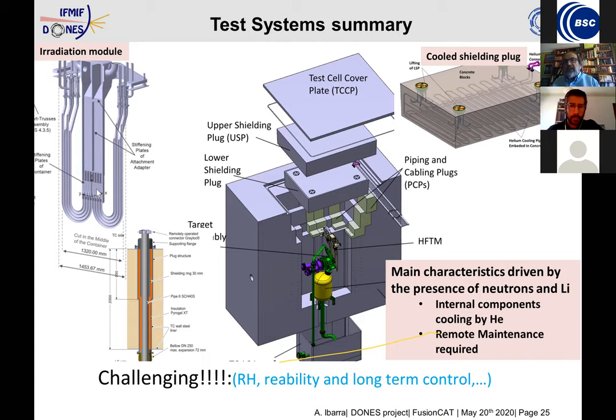And these packages have temperature control to a very high degree, less than a few percent, to assure the temperature stability along the irradiation time. Remember that we are talking about irradiation times of 1-2 years long. So we must be able to guarantee this temperature stability with low gradients in volume and low gradients in time. This is a key requirement coming from the materials people.